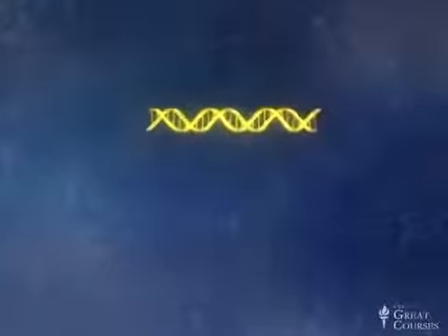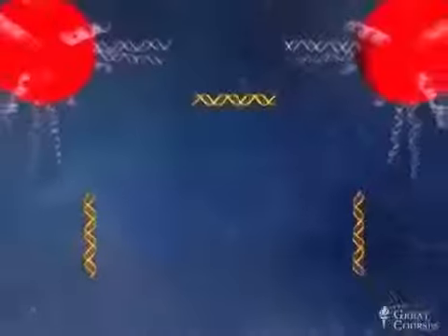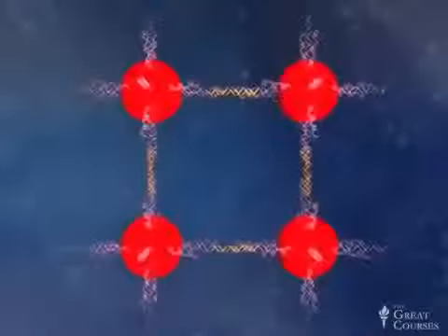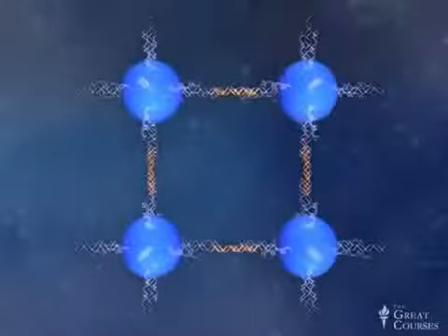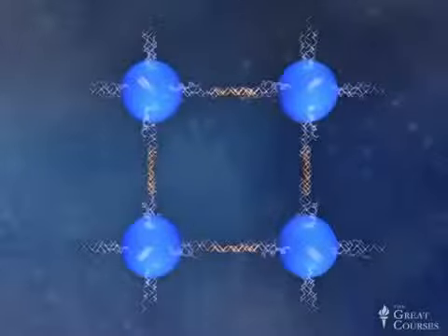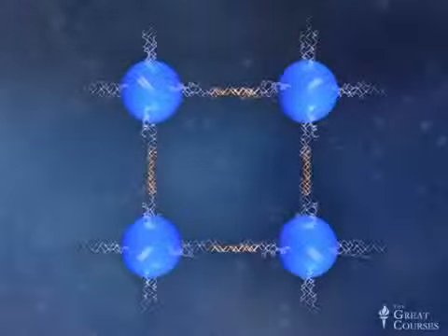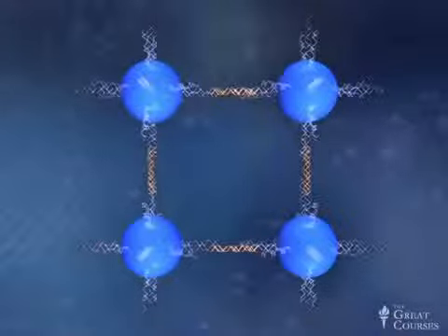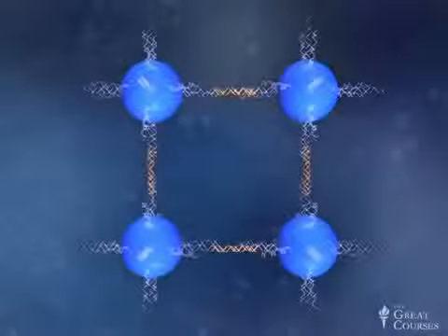Now, in order to detect the cystic fibrosis mutations, 2 different types of gold nanoparticles can be made that will line up specifically with the region of mutated DNA. And this is depicted schematically in the graphic that you're looking at, so hopefully you can see what's going where. If the altered DNA sequence is present, the gold nanoparticles will bind to it and they'll come together. And when this happens, the nanoparticles will change from red to blue. And it's that color change that tells us that the mutant sequence is present.